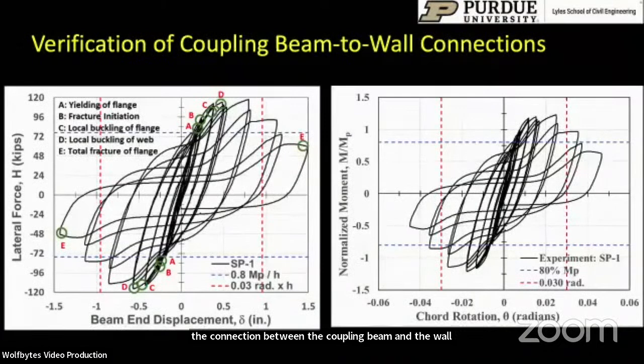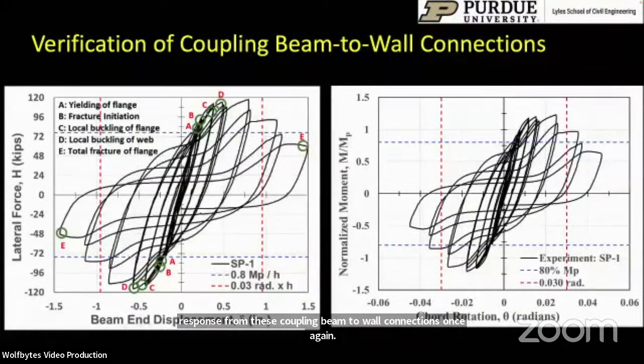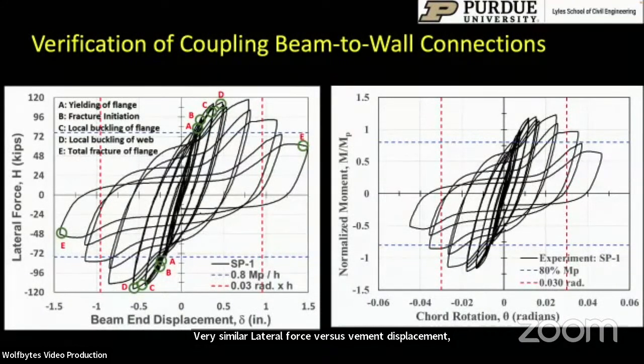Summary of the lateral load displacement response from these coupling beam to wall connections. Once again, very similar, lateral force versus beam end displacement. And the occurrence of various events along the lateral force are identified here, including yielding of the flanges, initiation of fracture, local buckling of the flange and the web, and then total fracture of the flanges. We took this force displacement and converted it into a normalized moment versus chord rotation response. And there's the line corresponding to 0.03 radians, which was the performance requirement for this connection.